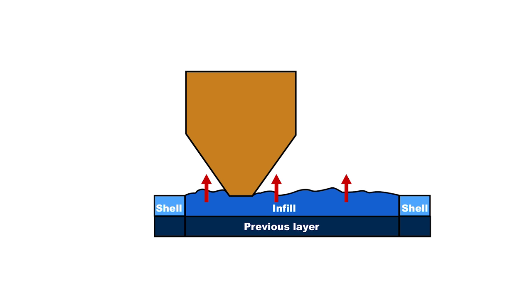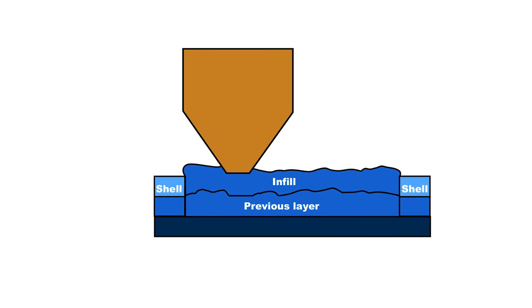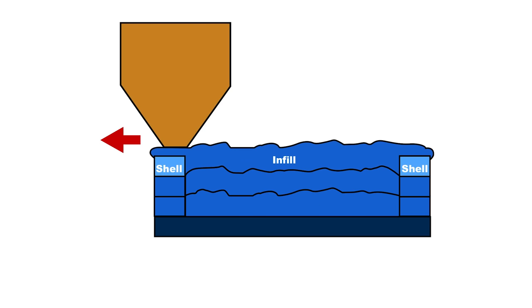As you print that molten plastic out, if there's not enough room for it, if you're over extruding, the only direction for it to go is upward. And as it does that, every layer builds upon the previous one, and you get more and more of an overage. Now, what's going to happen to all that plastic? Well, in some cases, it's going to get pushed out towards the edge and create a blob or a zit, or if it's a wide enough area, you're going to actually see a pretty sizable deviation in your layer line.